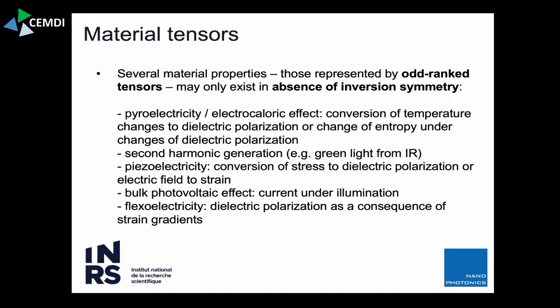And something that most of you probably haven't heard about is flexoelectricity. The moment that you take a centrosymmetric material and you bend it, you ever so slightly, as long as you stay in the elastic regime, change the symmetry. When you bend something, the outer side gets slightly extended, the inner side gets slightly compressed, you get strain gradients, and you can show from thermodynamical considerations that this gives rise to polarization. So these things don't exist if your material is centrosymmetric.